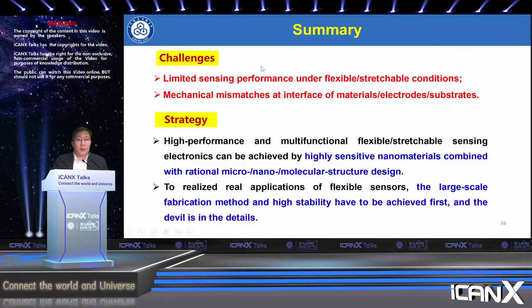Then we come to our summary. We think flexible sensors, or sensing electronics, are still in a very early stage. They face many challenges, such as limited sensing performance under flexible and stretchable conditions, and the bottleneck of mechanical mismatch at the interface of the material, electrode, and substrate. Our strategy is combining highly sensitive nanomaterials with micro-nano structure designs, and realizing real applications. We developed large-scale fabrication printing methods to achieve high stability and reliability. And we think that to develop real applied flexible sensors, the devil is in the details.